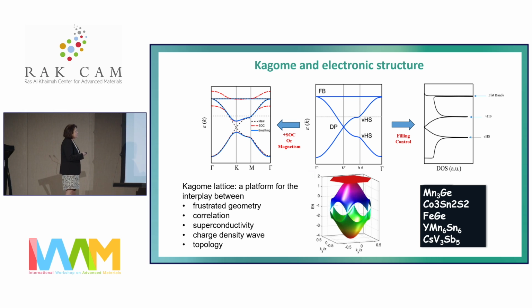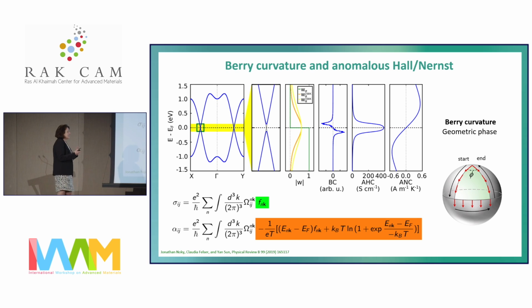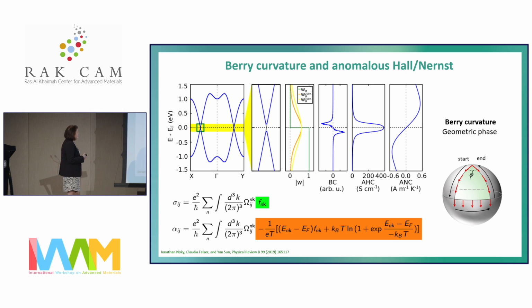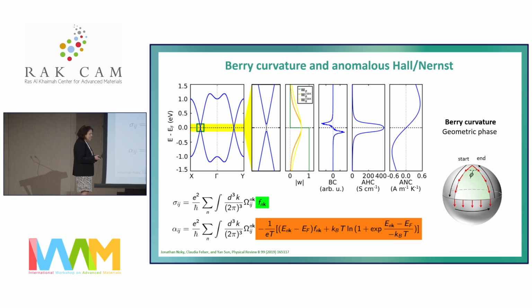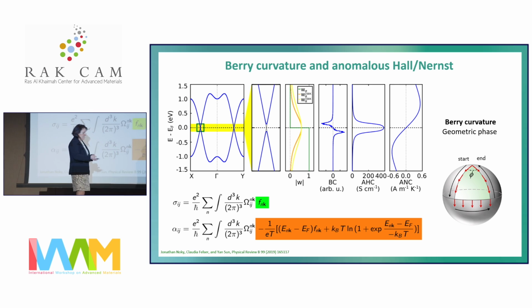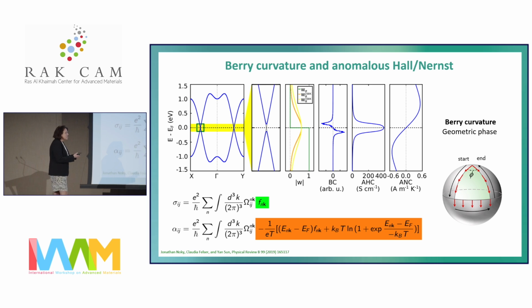So we have now, if we go to materials which have this Kagome lattice, the possibility to see frustrated magnetism, correlation, superconductivity, charge density wave, and topology. It's like you can do everything. So can we understand these materials and use design schemes to get interesting properties out? So from topology, we know if we have this crossing point in the electronic structure, this Y point, we can calculate the Berry curvature for this, which is simply a geometric phase. I always say in topology we do nothing else than we paint the bands which we have with colors of the Berry curvature, and simply we see totally new physics, because the bands which were before black, they are now red and blue, and we get very nice, interesting properties.